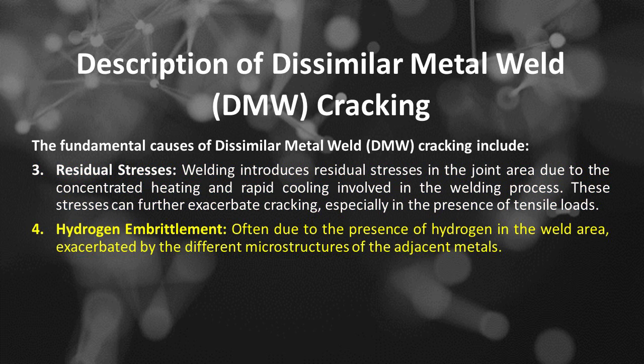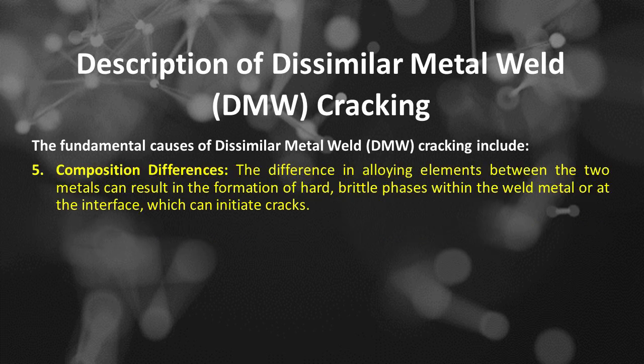Number 4 is hydrogen embrittlement. Often due to the presence of hydrogen in the weld area, exacerbated by the different microstructures of the adjacent metals. Number 5 is composition differences. The difference in alloying elements between the two metals can result in the formation of hard, brittle phases within the weld metal or at the interface, which can initiate cracks.